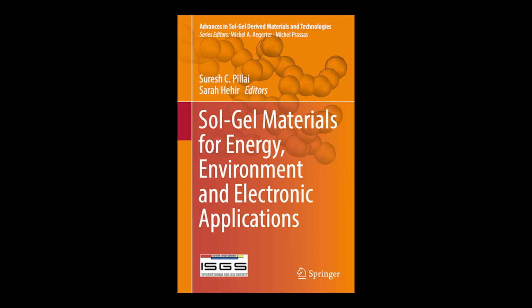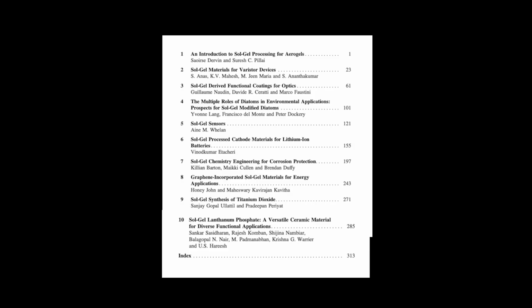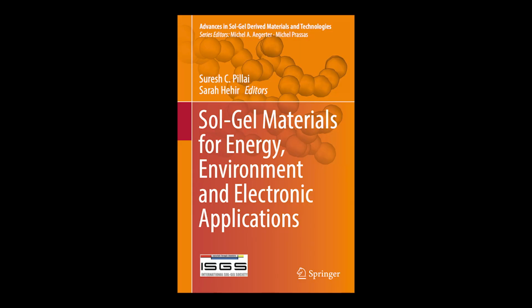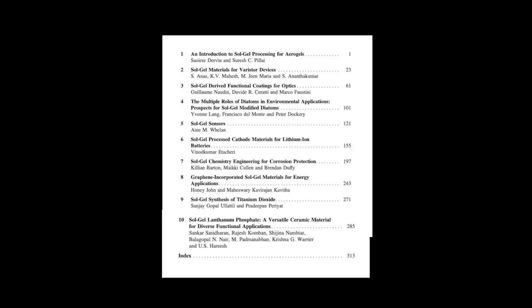Anatase generally has a higher adsorption affinity for organic compounds, meaning the pollutants stick to its surface better. But perhaps most importantly, it exhibits a significantly lower electron-hole recombination rate compared to rutile. Lower recombination meaning? Meaning when UV light hits the TiO2 and creates an electron and a hole, a positive charge, these charge carriers have more time in anatase to actually migrate to the surface and react with pollutants or water molecules before they simply find each other and recombine, releasing useless heat. A lower recombination rate means that charge carriers are more available to do the desired chemical work, maximizing the photocatalytic efficiency. Okay, so if anatase is so superior, why is stabilizing it mentioned as such a challenge in the chapter?